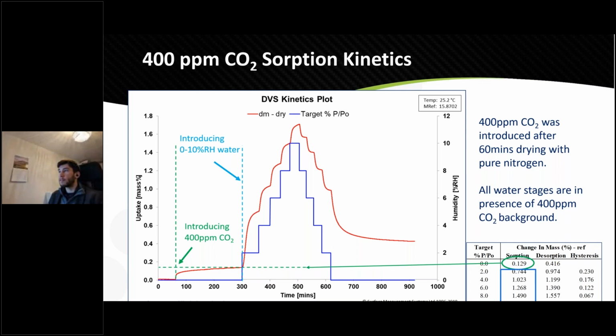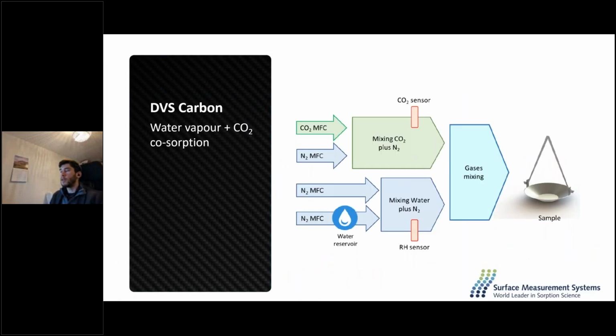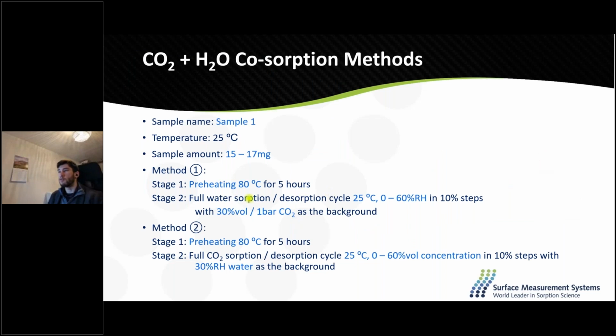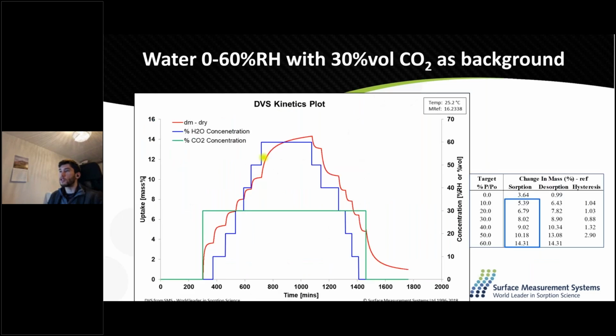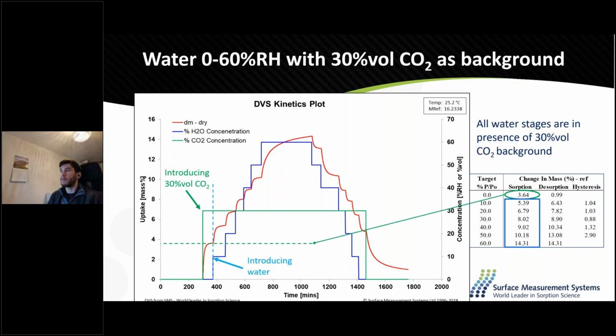Also, a couple of examples of mixing from the two sides, from the CO2 and water. These are two experiments in different configurations. One where the water was first introduced. The CO2 was introduced at 30%, equilibrated, and then a water isotherm on top, or the other way around, where we have a full CO2 isotherm recorded with a background of relative humidity. So we can see in green the CO2 concentration, in blue the water concentration and the mass. So introduction of 30% CO2, which is being kept constant as water is being ramped up and down. And this is the other way around, where we have a background of humidity, and afterwards CO2 is being introduced on top.